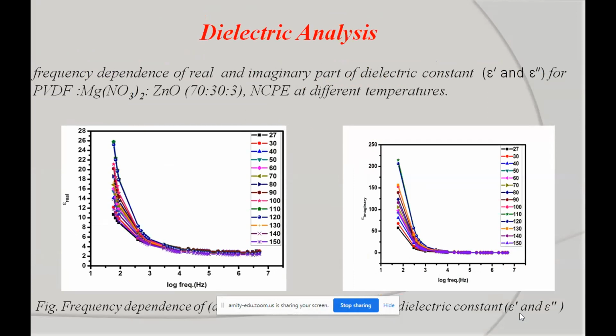In this figure, it is observed that as the temperature of the electrolyte increases, the dielectric constant value also increases. And the second observation was, as frequency increases, the dielectric constant value gets saturated at higher frequencies in both curves.